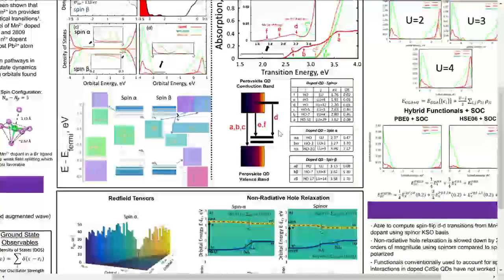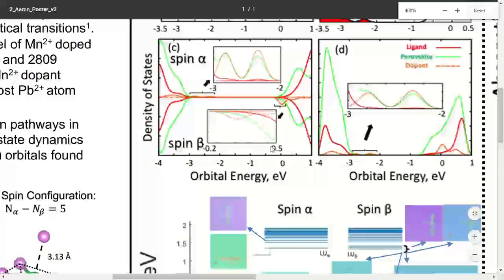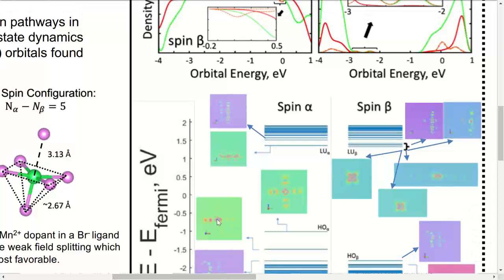Did you take a close look at the PDOS? So what is the degree of hybridization for these two atoms? It's about 40% metal ion, or manganese orbitals, about 40% bromine p, and then the other 10% is either ligand or s orbital, or Pb s. I guess it's higher, well, just looking at the image you can tell, that's for the topmost state. This one, I think it's still 40% of the bromides around it, but it's less of the d metal.